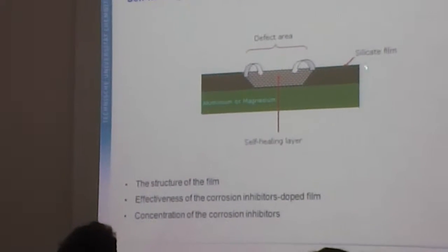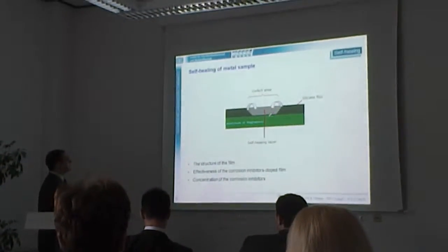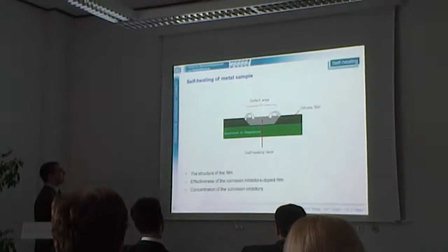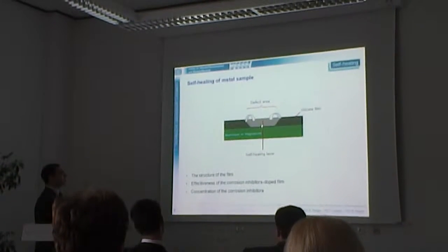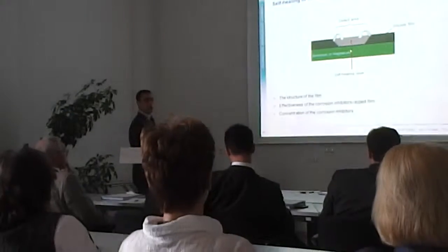Here, a corrosion inhibitor is stored in the silicate film, and this film was deposited on an aluminum or magnesium substrate. When a defect appears in the film, corrosive solution penetrates into the defect area, reaches the substrate, and the corrosion starts. Also, corrosive solution penetrates into the structure of the film. The corrosion inhibitors leach out of the film to the defect area to form a layer. This layer can be called the corrosion inhibitor layer or self-healing layer, which prevents the effect of the corrosive solution.